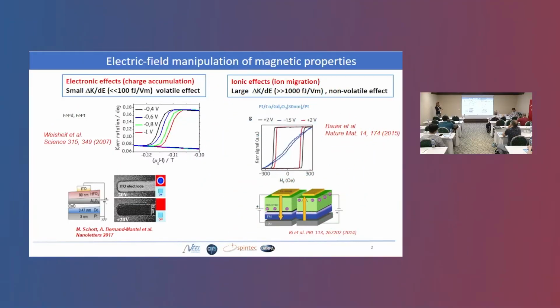So electric field manipulation of magnetic properties was pioneered in our group by my colleague Dominique Givord in 2007, and they showed that in thin iron platinum and iron palladium layers, by applying an electric field, this time in a liquid electrolyte, they could change the magnetic anisotropy by a few percent.